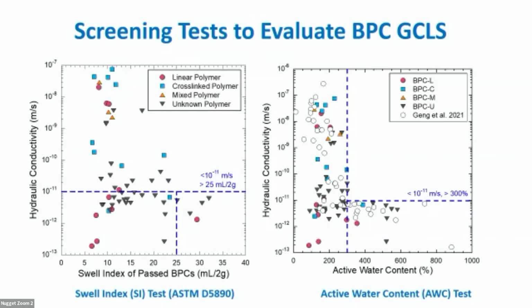A swell index test, which is conventional for sodium bentonite GCLs, turns out that doesn't work very well at all. The one that we use for conventional GCLs doesn't work. We've been looking at this active water content test as well. We'd like something that we can run in a couple of days to get a sense whether it's going to work or not. We're not quite there yet. This active water content test does seem to be a discriminator, whereas our swell index test really just gives us a bunch of noisy data.